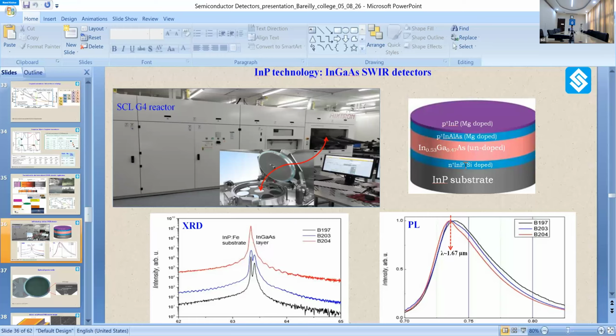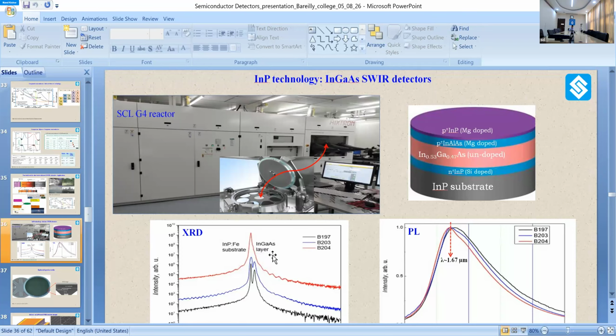Okay, so during the growth itself, we actually create our PN diode on top of either the gallium arsenide substrate or the indium phosphide substrate. Okay, so after growth, what do we do? We mainly do the material characterizations. How good is my material, or what is the quality of the material grown on the substrate. Okay, so for that we mainly do X-ray diffraction measurements. Basically, we have to check whether there is any kind of lattice mismatch present in the layer or not. So you can see if there is a lattice mismatch, there is a distinct peak between the epitaxial layer and the substrate material. If it is a perfect lattice match, there is a single peak in the XRD, and this will confirm that the layer quality is very good.